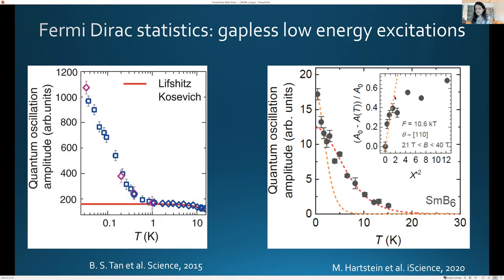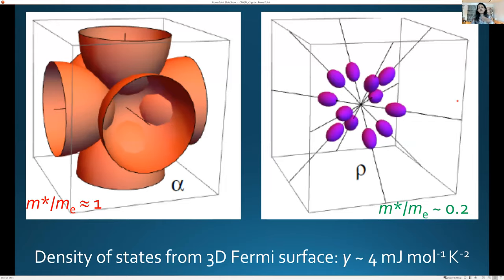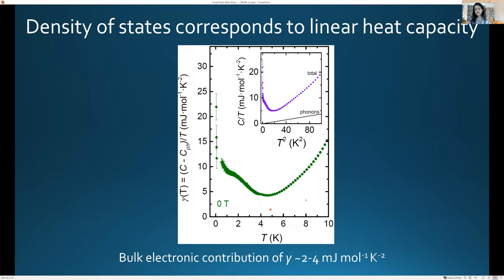And I'll show you the formula in a few slides to show that this is inconsistent with a gap at the Fermi energy. It is most closely consistent with a gapless low energy excitation at the Fermi energy. We can also do a very rough back of the envelope calculation and say for this size of Fermi surface, these are very light masses we measure from Lifshitz-Kosevich, so you get roughly masses of about 1 or 0.2. The density of states would be about 4 millijoules, which is not too dissimilar from the linear heat capacity that is observed. So this was actually observed several decades ago in the 1980s or 1990s by groups that were studying it at the time, who commented there appears to be this finite linear heat capacity.